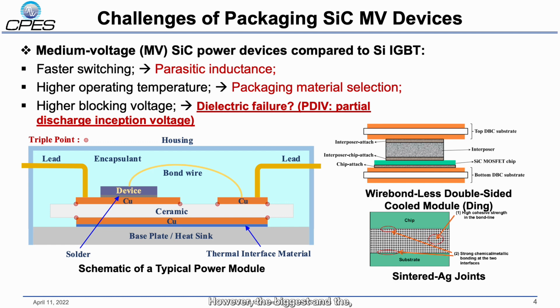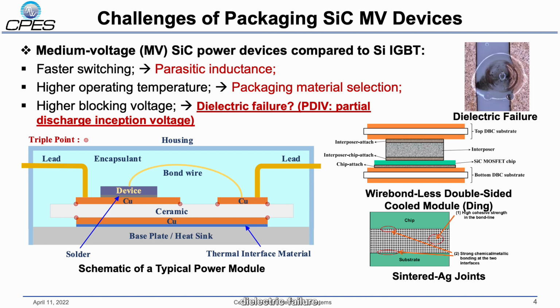However, the biggest and the most unique challenge is from the higher blocking voltage. The insulation materials, especially the ceramic in the substrate and the encapsulant in the module, are facing much higher electric field and causing the dielectric failure. People use the partial discharge inception voltage to quantify the insulation performance of a power module. This presentation's focus is to improve the insulation without sacrificing other performance of the package.